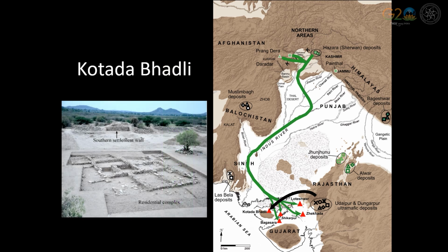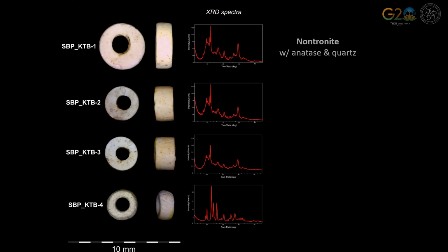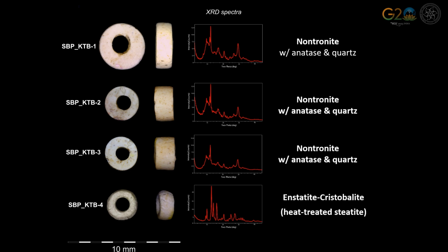It should be noted here that Kotada Bhadli is not strictly an Indus Civilization site. Rather, it is a contemporaneous site of Sorath Harappan affiliation. Four beads from Deccan College's excavations were analyzed. One, like I have indicated, was made from steatite sourced to Rajasthan. Now, this is not typical of Harappan bead makers, clearly. The other three beads were not even steatite at all. X-ray diffraction analysis indicated that they were made from a locally available clay called nontronite.